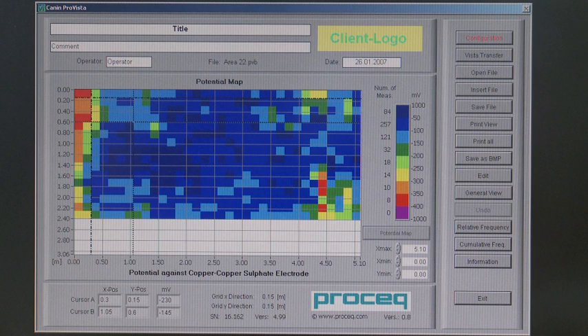Canin ProVista is used to estimate a threshold potential, below which it is assumed that the concrete is corroding and above which it is assumed the concrete is healthy. This threshold potential is a variable which must be determined for each individual concrete using statistical methods and also verification by further inspection. For the evaluation of the measurements, Canin ProVista offers two statistical presentations: the relative frequency and the cumulative frequency graphs. By use of these representations, an individual determination of the threshold potential is easily possible for each structure and for single sub-areas.